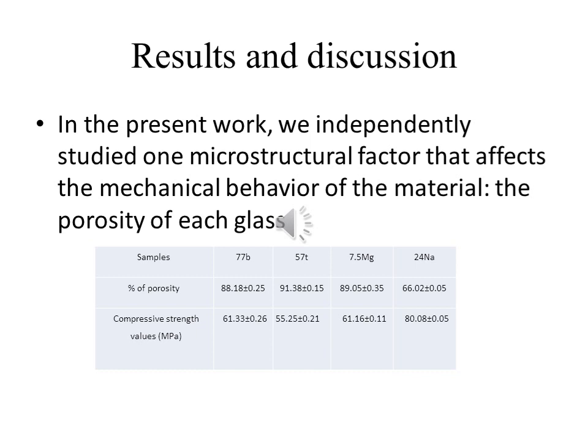For the glass with sodium, we can observe it has a good compressive strength, with 66.0% of porosity. The ternary glass presents modest compressive strength with high porosity, 91.4% of porosity. We can say all glasses have a good percent of porosity, and the compressive strength is modest.